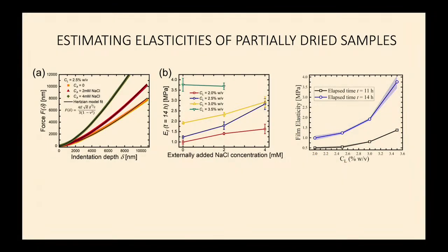Here's our result from the micro indentation measurements. These are the force-indentation depth plots that we have for the same clay concentration, but with different sodium chloride, common salt, concentrations. This is just representative data. We've taken hundreds of data points here. As you can see, probably because of the spherical approximation of the tip that we made, it does fit a Hertzian model, and it lets us estimate the Young's modulus, which we've plotted here.